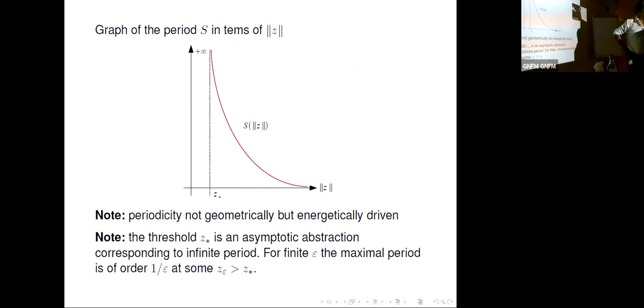So if you want the periodicity, the period is infinite, so infinitely apart. Then at some point you start having cracks, and they come with the period lower and lower as the deformation increases. So this is in accordance, if you want, for the first picture in which you see layers of cracks close to the eyes of Mona Lisa, which are aligned to a single direction and they're more or less periodically distributed.